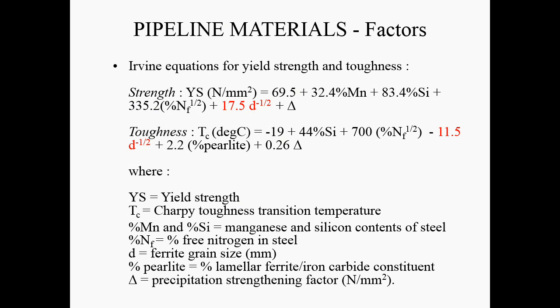In fact, this is one of the processes where metallurgy at Newcastle, and I say at Newcastle because I mean Newcastle, Australia, and Newcastle in the UK. Norman Petch was here, Edmund Hall was in Australia at Newcastle, and then they did the work which empirically showed that the increase in strength due to grain size is due to a constant divided by the reciprocal of the square root of grain size. Norman Petch then went to Leeds, and he did a lot of work at Leeds University as well, but he was here briefly. So you could say it's a Newcastle invention or discovery back in the 1950s. But the point about this is you can increase strength and you can increase toughness by making the grain size small. So that's why grain size control has been so important.